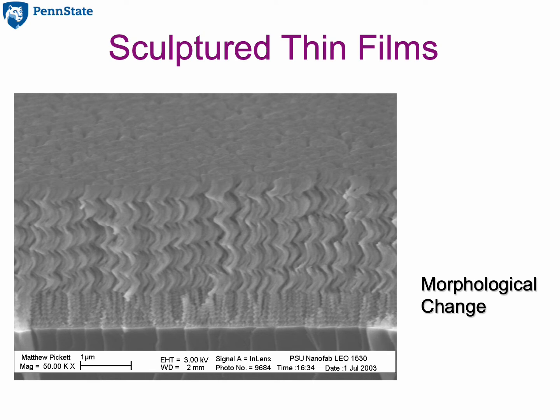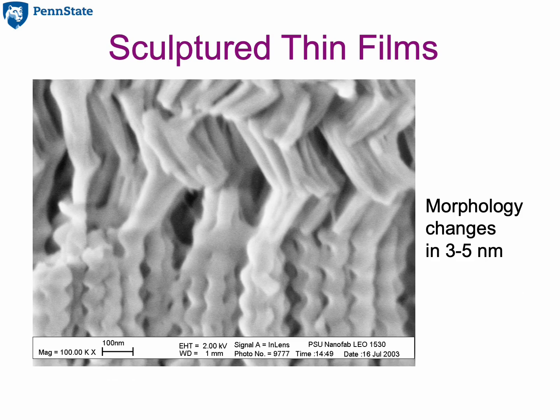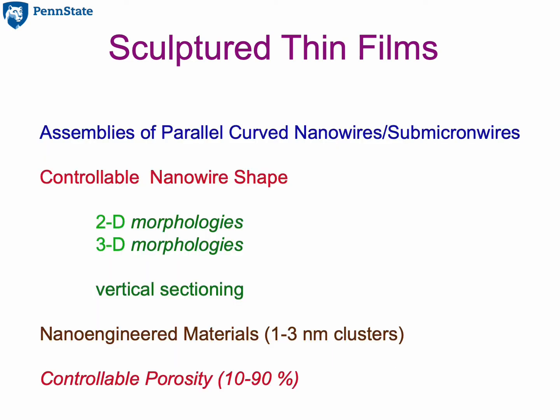As the nanowire assembly grows, the shape can be changed almost abruptly. Here you see helical nanowires with the pitch changed abruptly almost midway through the sculptured thin film. The abrupt change in nanowire shape occurs within 3 to 5 nanometers of growth. This is because sculptured thin films comprise clusters of 1 to 3 nanometers as building blocks. The inter-nanowire as well as the intercluster porosities can be controlled by varying the deposition conditions.